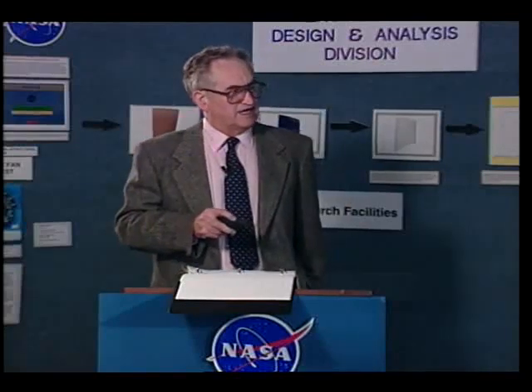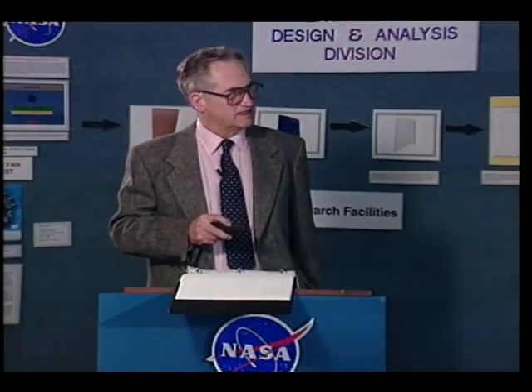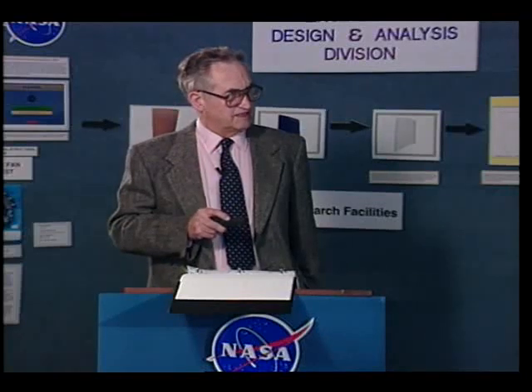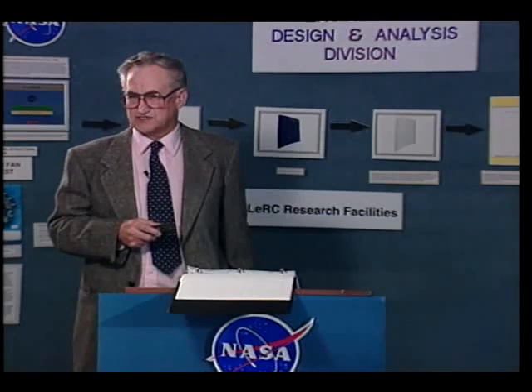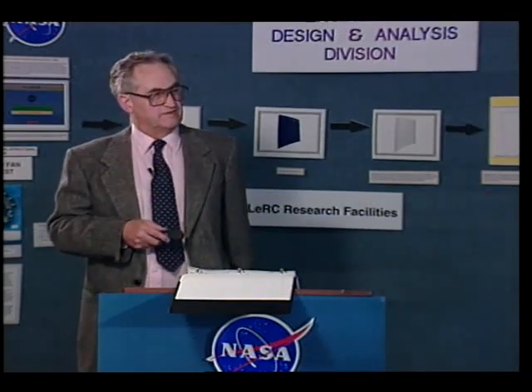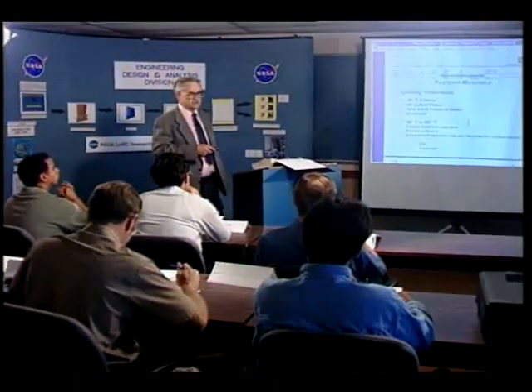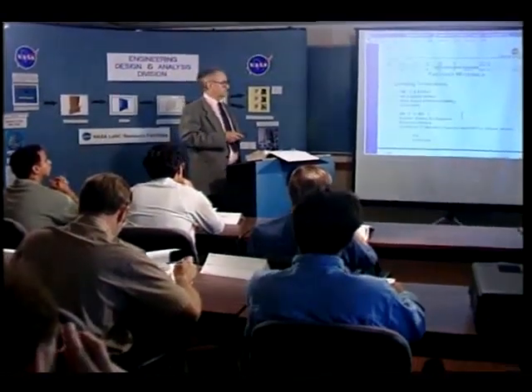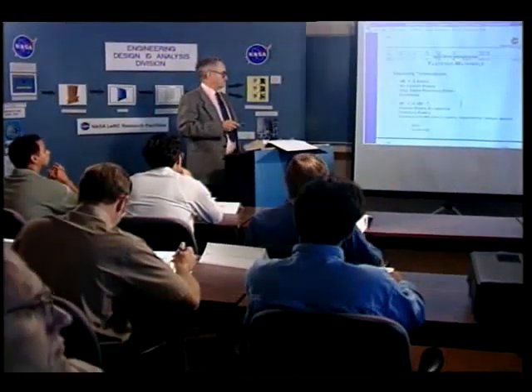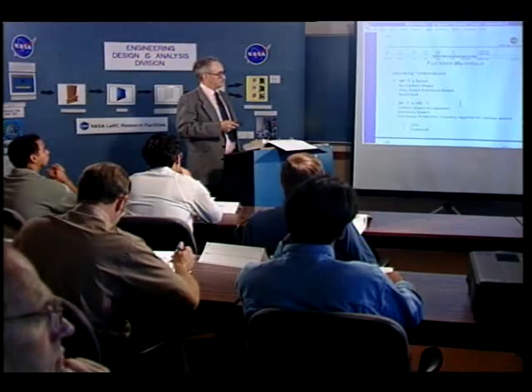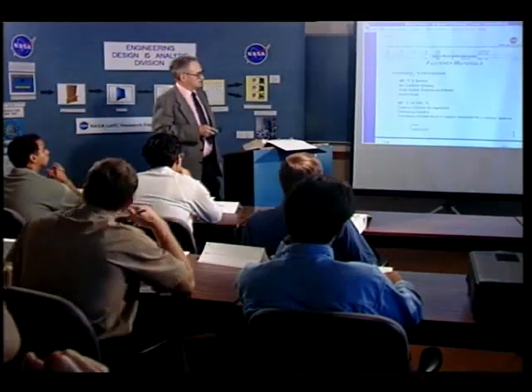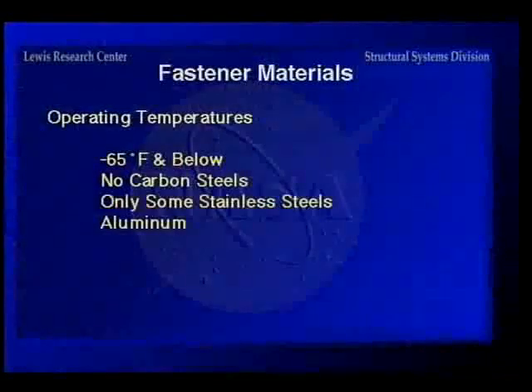Here I have grouped this in categories, and so the minus 65 and below, that's your cryogenic temperatures. Now, of course, those of you who have been around long enough remember the Atlas and Centaur. And, of course, they're liquid hydrogen fueled, so the temperatures you're running on that type of a vehicle are anywhere from about minus 300 to minus 423. So you cannot use carbon steels at those temperatures because they will crack like glass.